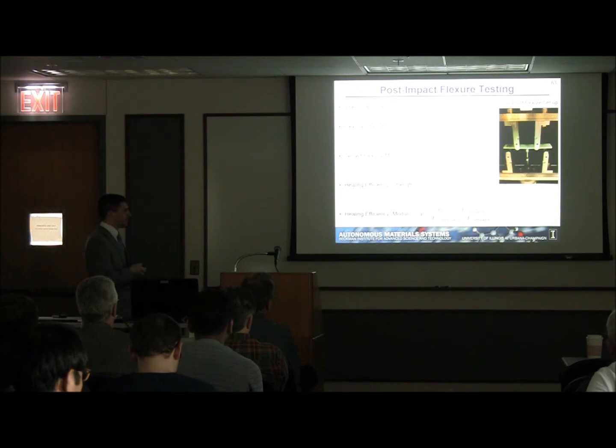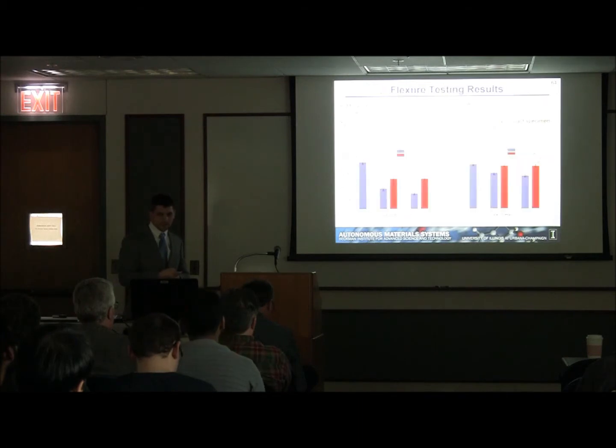After allowing 48 hours at 30 degrees Celsius for the healing to take place, we test these samples in post-impact flexure again. Our outer span is 80 millimeters, inner span 40 millimeters. Again, we're looking at flexural strength and secant flexural moduli. But now we can define two metrics of healing efficiency for both the strength and the moduli: the healed minus the damaged flexural strength divided by the undamaged minus the damaged strength, which is similar to healing efficiencies previously observed. Similarly with the moduli, healed minus damaged over undamaged minus damaged.